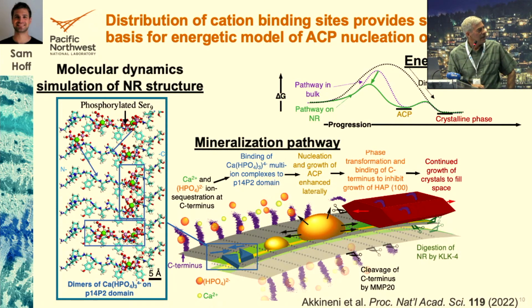And it turns out that these phosphors assemble into the beta sheet. And when you look at where these phosphorylation sites are, they're really well positioned to match the structure of this calcium triphosphate unit I mentioned yesterday, that is the starting unit for making amorphous calcium phosphate. And so we end up with this really nice model where we have a low interfacial energy interface, but we have ion binding sites that sort of template the multi-ion units that start the amorphous phase.